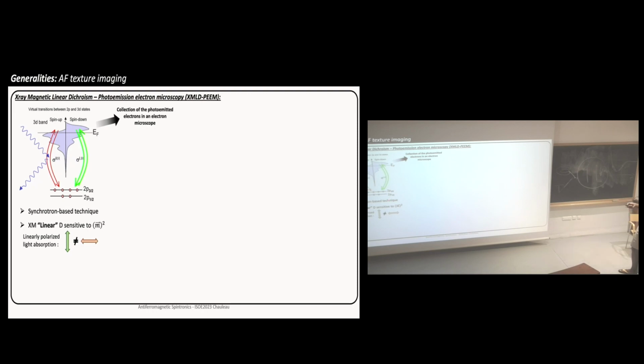So if you collect the photoemitted electrons with respect to linearly polarized light in one direction versus another, and you look at the contrast, to some extent, you can have magnetic contrast. This is what I will detail a bit later, but what you also need to know is that you are also highly sensitive to crystal anisotropy, and this is where these techniques can have some drawbacks.